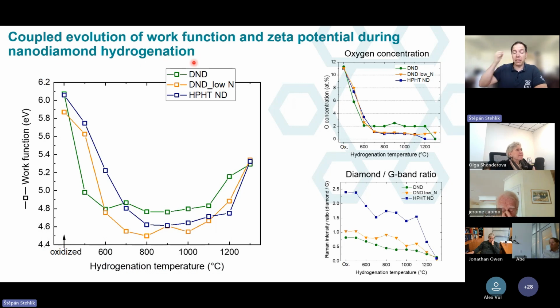So here, this is an important graph showing the evolution of the work function for these three nanodiamonds as a function of the hydrogenation temperature. So it's actually as expected, and also as indicated by the previous study. But what is nice is that we made this kind of dependence as a function of the hydrogenation temperature.